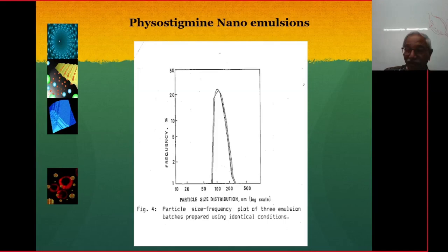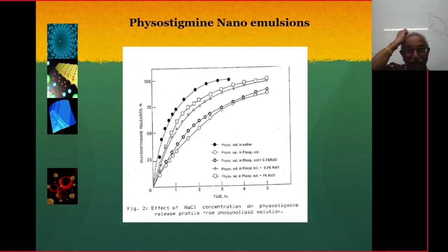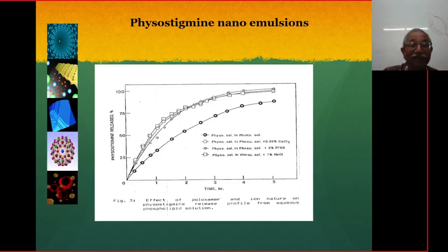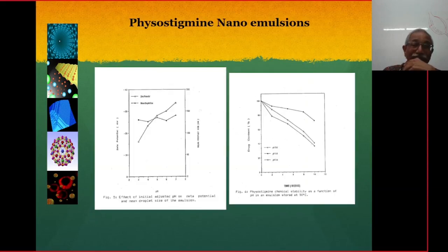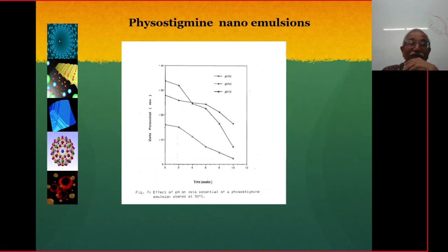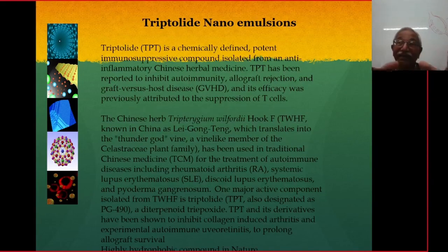So we studied the drug release of the nanoemulsion. So you can see the drug release over a period of time. It goes in 5 hours. Now you have to understand that we do this drug release in 900 ml of water, but you will never get 900 ml in the body at one time. So obviously it can be extrapolated to many more hours. Then this is another drug release study which we did in the dissolution apparatus. This is the degradation we studied at different temperatures, and showed the stability of the nanoemulsions, and the physostigmine nanoemulsion degradation we have shown. And then what we did was we studied the absorption of the nanoemulsion.